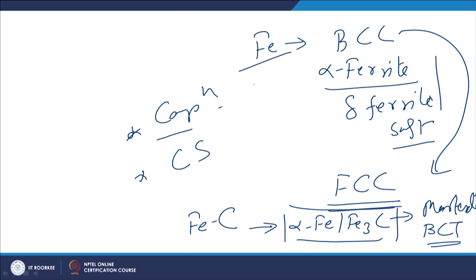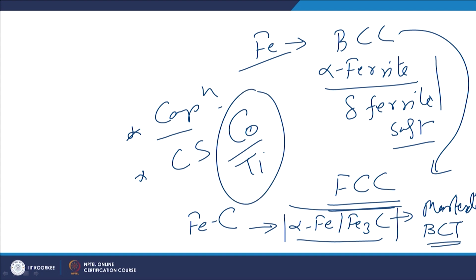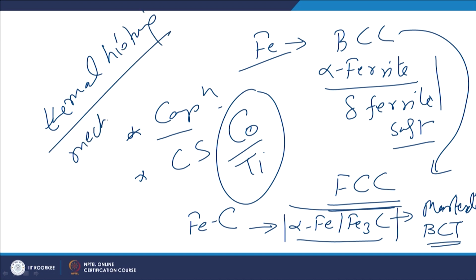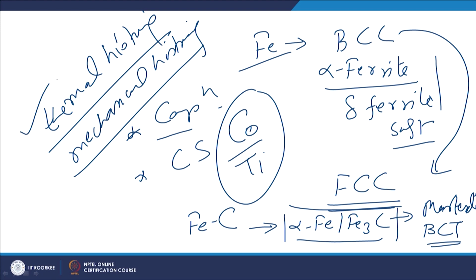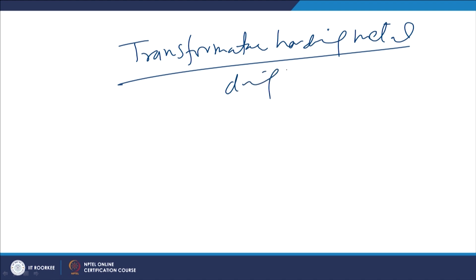Likewise iron, cobalt and titanium alloys also show such transformation behavior, where a change in the thermal history or the mechanical history of the material during processing, either controlled heating followed by cooling or controlled plastic deformation of the metal, leads to phase transformations, where the change of phase leads to an increase or decrease in mechanical properties. So, in which way will the transformation hardening metals be behaving during the welding?